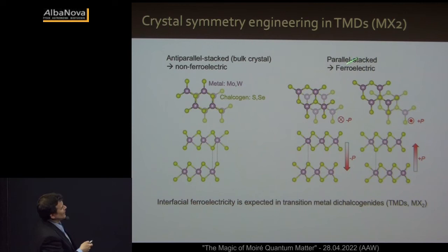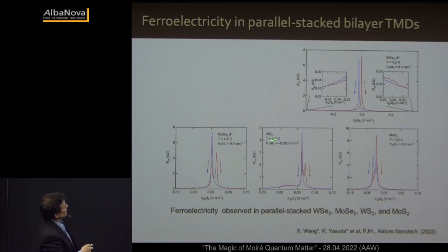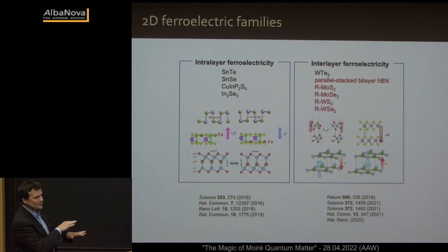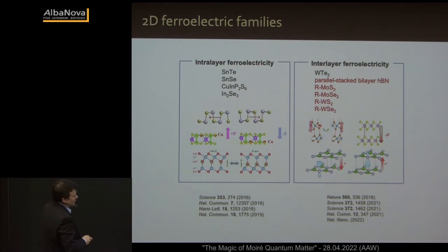So we made this with all the transition metal dichalcogenides, the semiconducting ones, WSe2, MoSe2, WS2, MoS2. All of them are ferroelectrics. All of them work at room temperature, and they are semiconductors. So you can do logic and memory in the same device at once, okay? So with this work in the past year, we basically doubled the number of two-dimensional ferroelectrics that we have, using these Moiré structures and this stacking engineering.